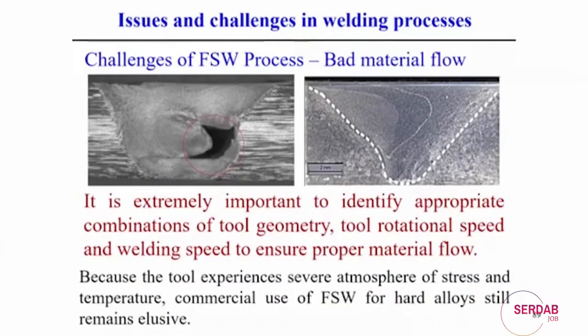But the challenge mainly is insufficient material flow. If we look at this figure, it is a welded joint, but we can observe some small gap. That happens because the material flow is not good, and it can create this kind of problem. On the right-hand side is a good weld joint, joining these two components in the solid state welding process. Therefore, it is extremely important to identify the appropriate composition of the tool, the appropriate tool geometry and the other welding parameters, tool rotational speed and welding speed, that ensure proper material flow. Then with this combination of parameters we can expect a good weld joint.